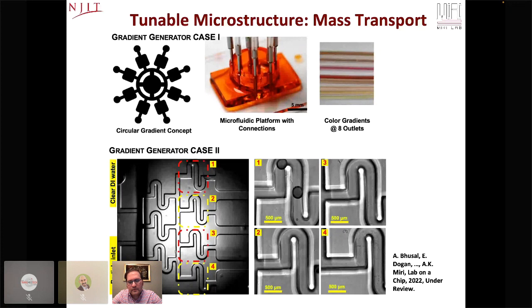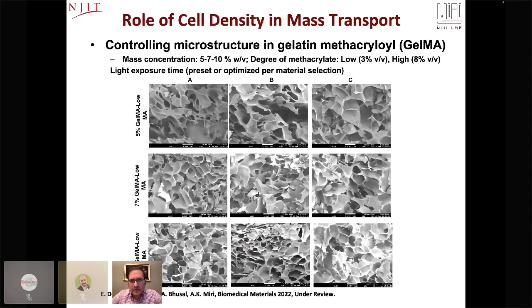So you can see here, we wanted to show we can create gradients with 8 chambers. And also we could see the quality of our fabricated construct when you're looking at small channels, for example, if you want to use for mixing phenomena, or you want to use for even particle separation. So now we show that capacity, and then we show that we can change the cell density. When you are working with GelMA as the main bioink here, you want to encapsulate cells in GelMA, and you want to use it in our bioprinting process.